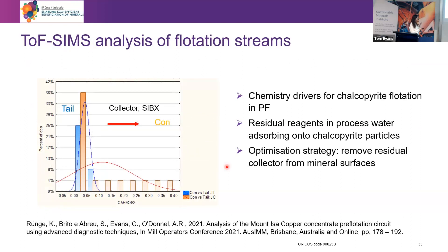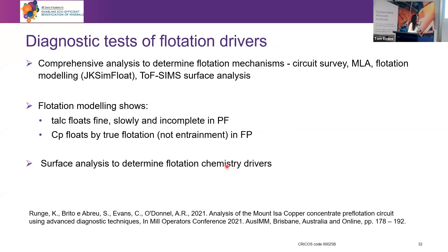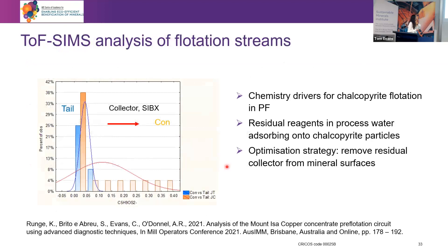Flotation modeling showed that the talc floats very finely and slowly and is incomplete, and the chalcopyrite floats by true flotation and not by entrainment, which had been hypothesized at the beginning. We then conducted surface analysis to determine the flotation chemistry drivers. When we looked at the concentrate versus the tail samples collected from the plant, we found that there are collector molecules on the chalcopyrite particles that floated. In that part of the circuit, no reagents are added because they don't want to recover chalcopyrite — they just want to remove talc. Therefore, the collector was coming from the process water as a residual reagent.